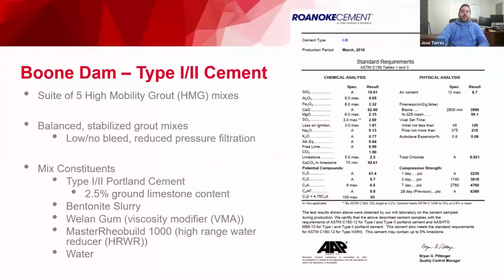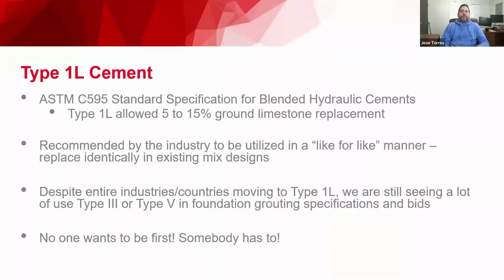So I already talked about this—ASTM C595, Type 1L is 5 to 15% ground limestone. They recommend you use it basically in a 1-to-1 replacement. So if you're using Type 1, Type 2, Type 3, or even Type 5, they make it real simple: just put the same amount of Type 1, 2, 3, or 5 that you were using in your mixes and replace it with 1L, then see what happens, using a like-for-like manner.